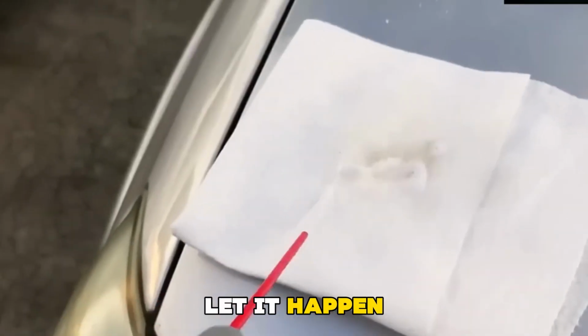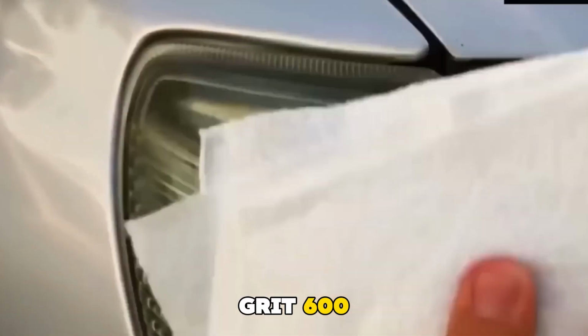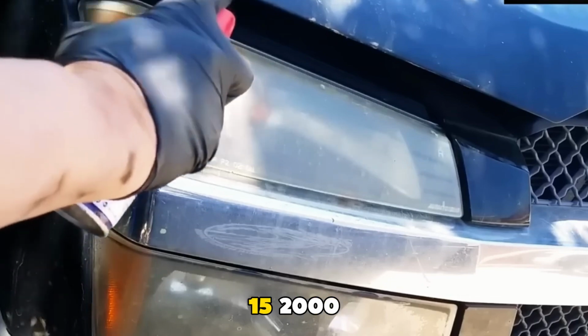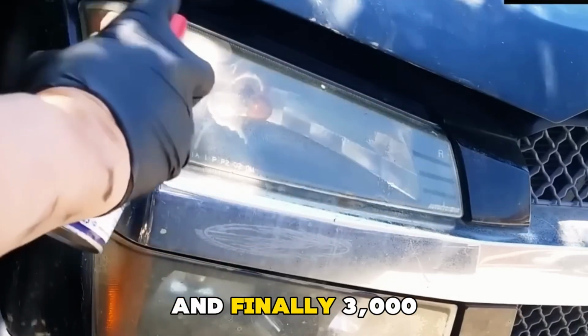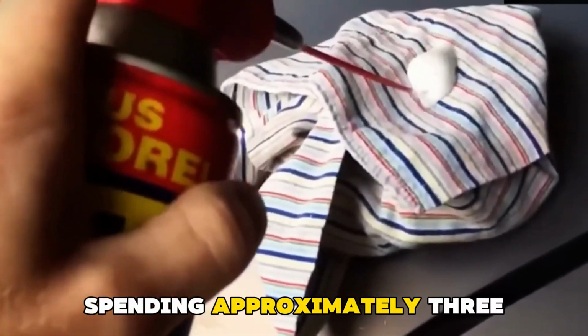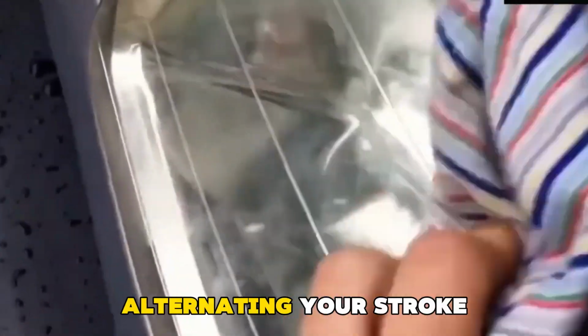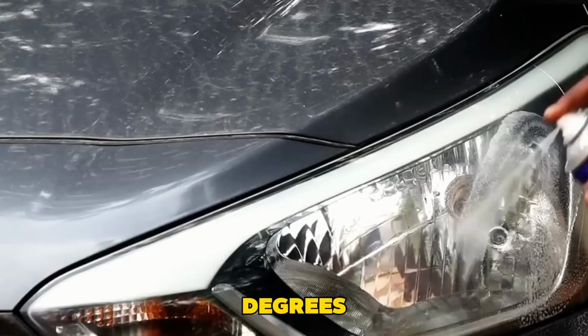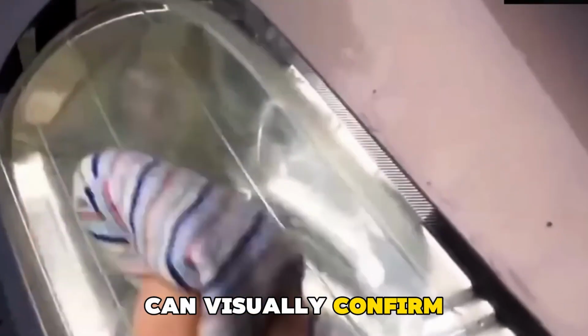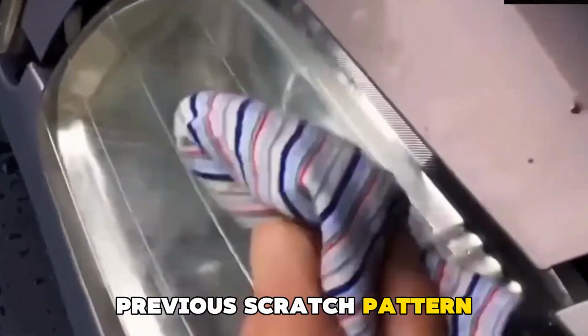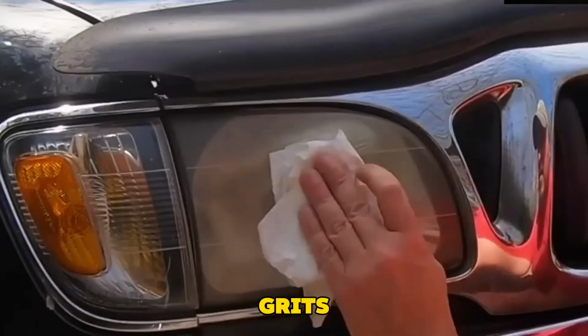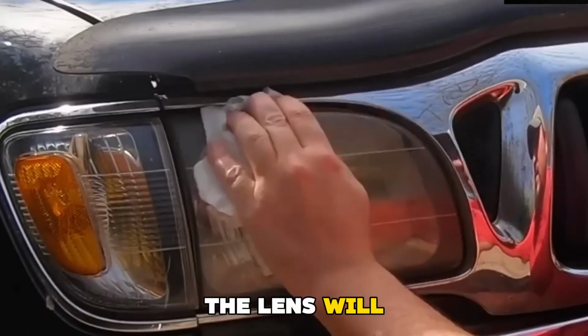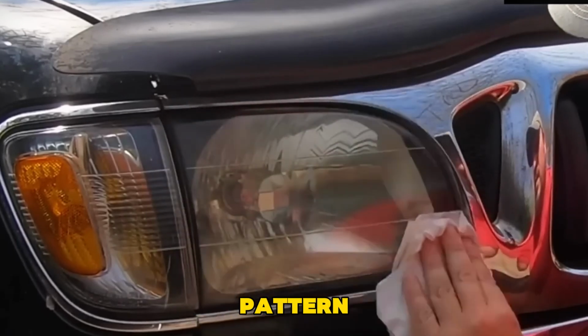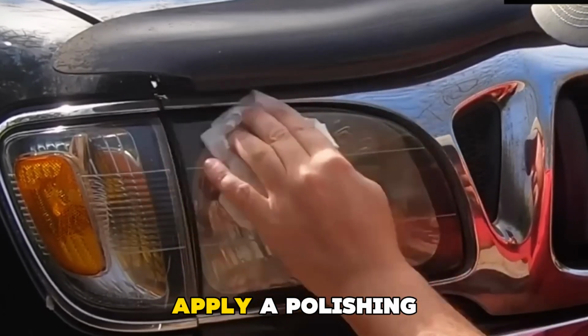Let it happen. Work through each grit, 600, 800, 1000, 1500, 2000, and finally 3000, spending approximately 3 to 5 minutes per grit, alternating your stroke direction by 90 degrees with each new grit so you can visually confirm you've removed the previous scratch pattern. Rinse thoroughly between grits. After 3000, the lens will look hazy from a fine scratch pattern. That's completely normal. Apply a polishing compound by hand or machine to refine the surface to optical clarity.